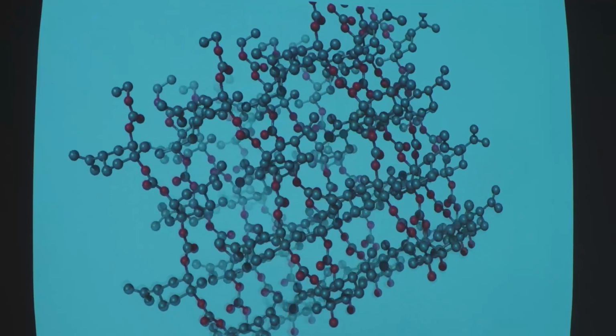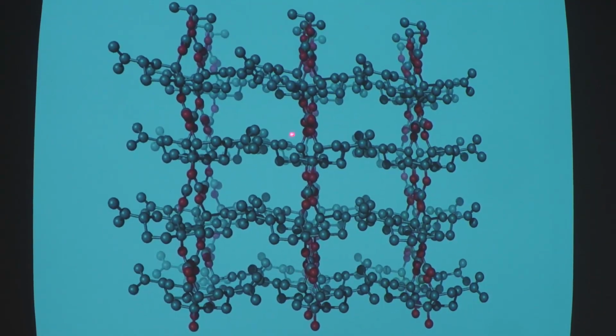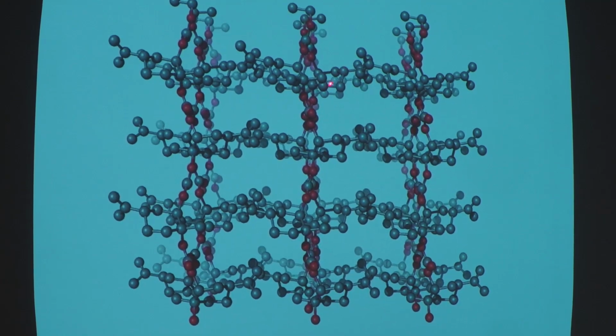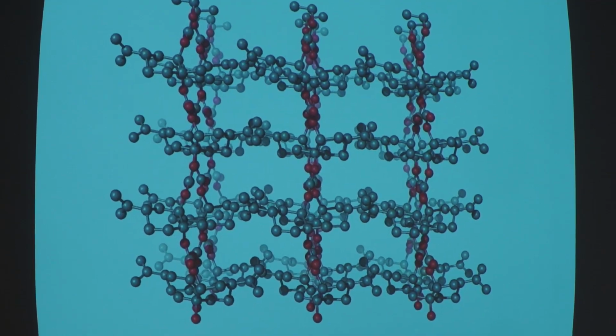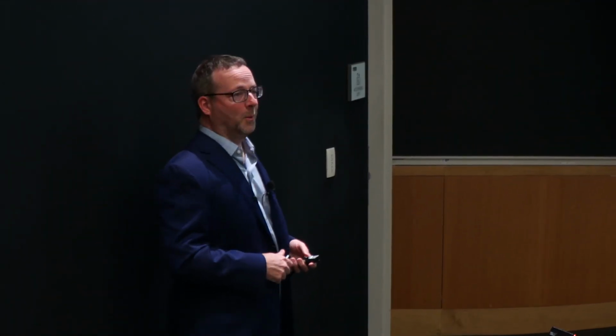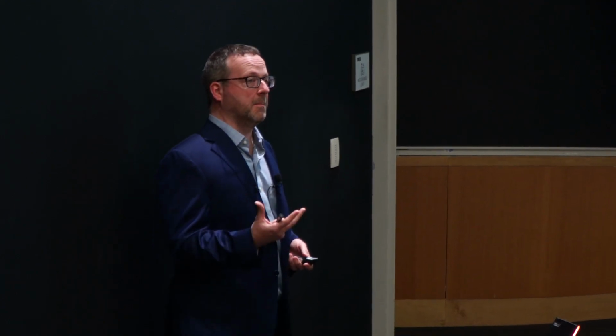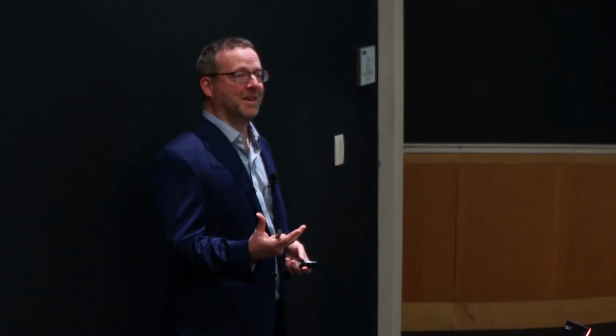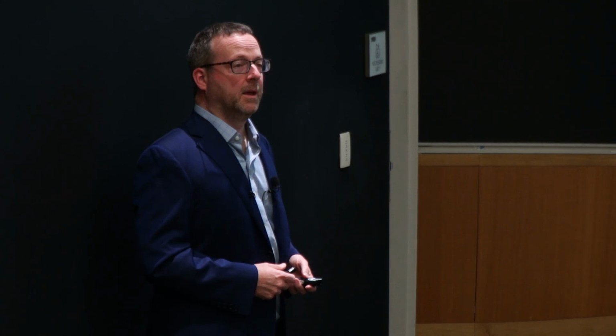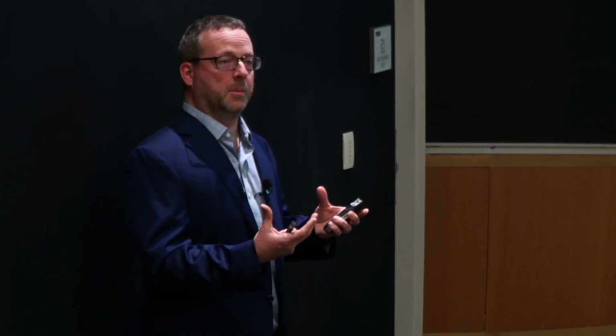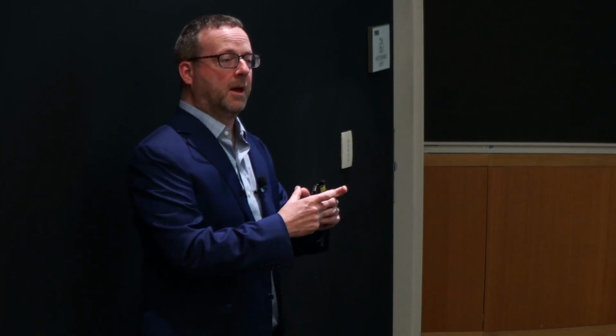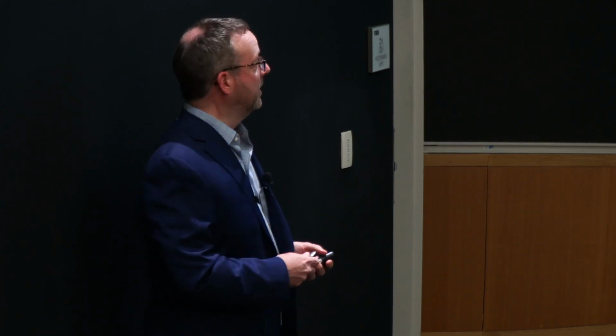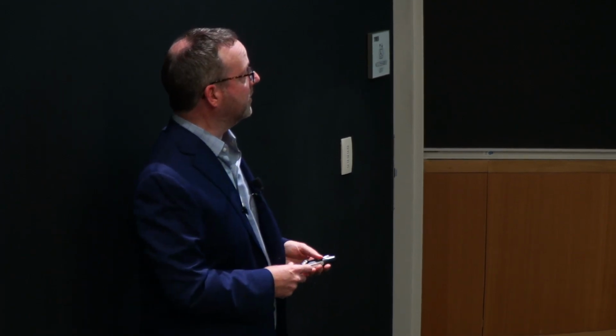And my crystallographer did one last turn here that makes you a little dizzy, but now we're back where we started. So you can see this one here has a ring, this one here has a ring, and they basically can zipper together and interdigitate in a way that they don't if you only have one enantiomer. And you might say, well, what's that good for? Well, first of all, these are really high melting. Actually, they're too high melting. They're so high that if you try to melt the polymer, it decomposes, so it's over about 180 degrees. But it's really interesting as a supermolecular synthon that we're trying to grow and put on different molecules as a way to bring them together and make supermolecular assemblies through what I think are some pretty interesting stereocomplexations.